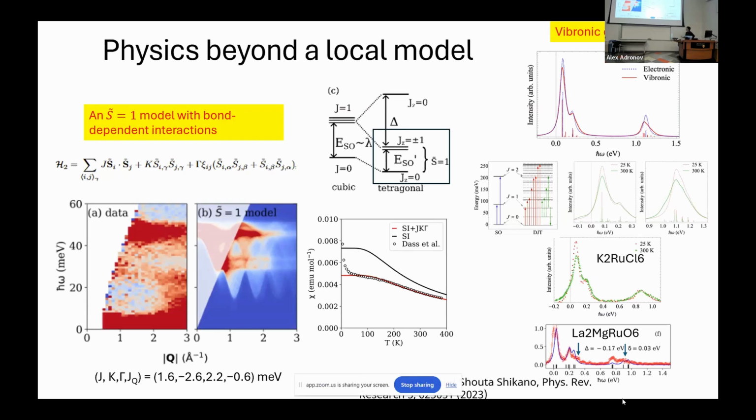So if I take this exchange coupling, plug it in, and calculate on the mean field level what the susceptibility looks like, it's a pleasant surprise that it matches the data exactly. But if you use the single ion model from RIXS and calculate what the single ion susceptibility looks like, it overshoots your data by quite a bit. So this tells me that exchange might be relevant here.